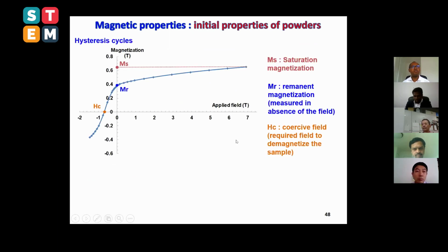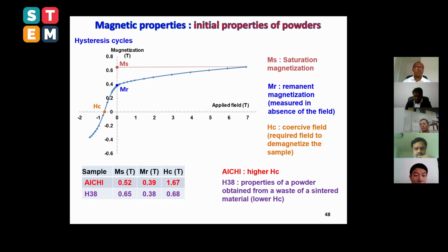And how about the magnetic properties of this? But before giving you the result, let me show you what we deduce from all this. Magnetically, we make the hysteresis cycle. And from the hysteresis cycle, you are going to deduce what you call MS, the saturation magnetization. And then you are going to use also MR, the remnant magnetization, when the applied field is zero. And the last parameter is HC, the coercive field. And we perform this first on both powders. Here you have the characteristics and the results you obtain in both powders, Aichi and the recycling powder.